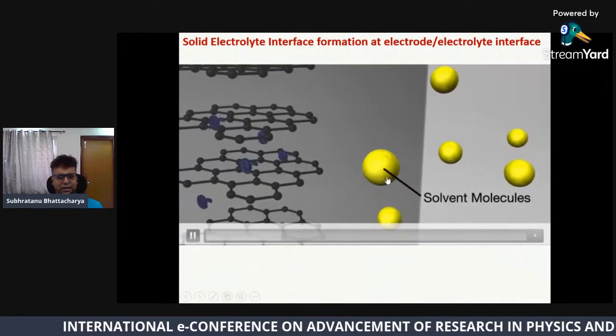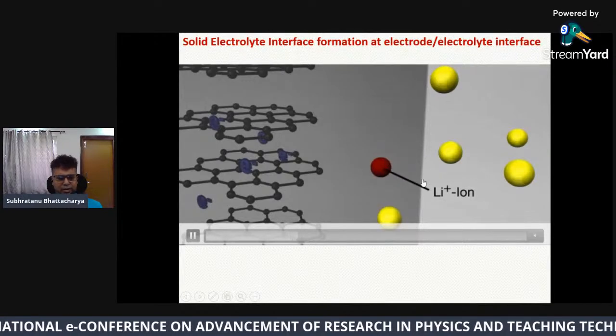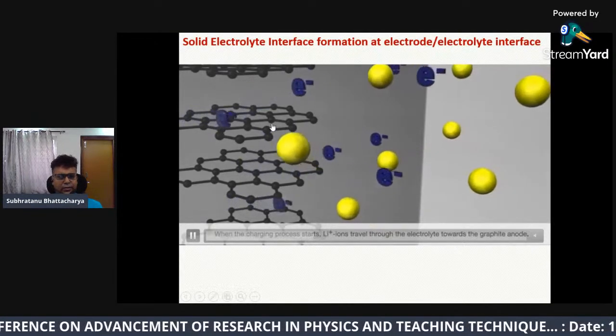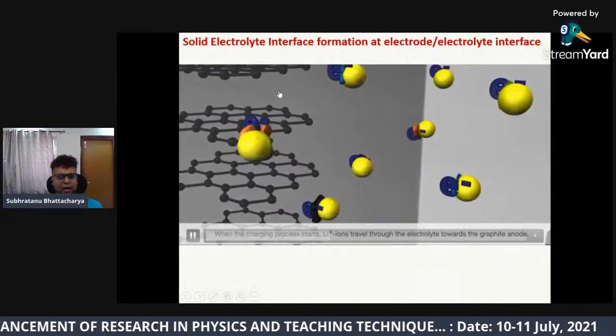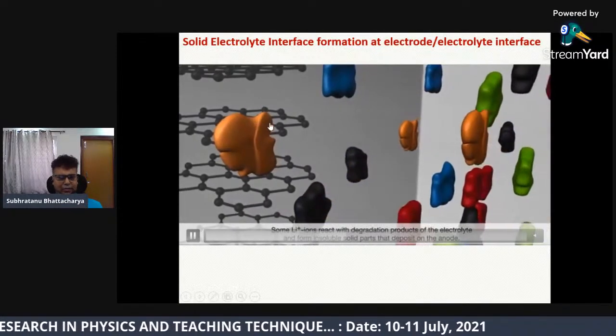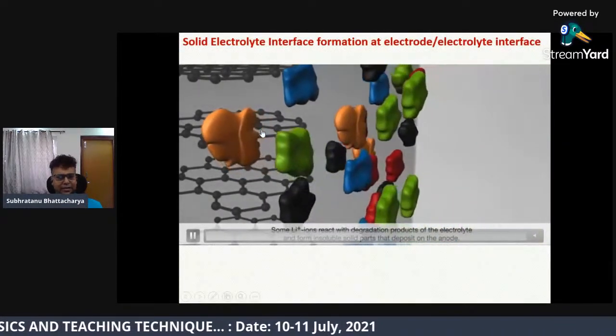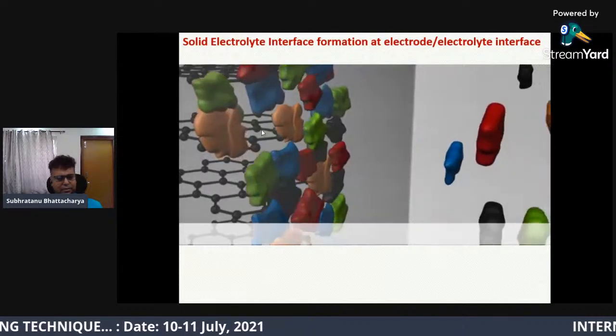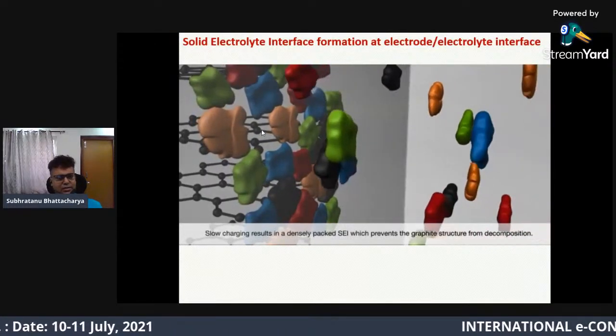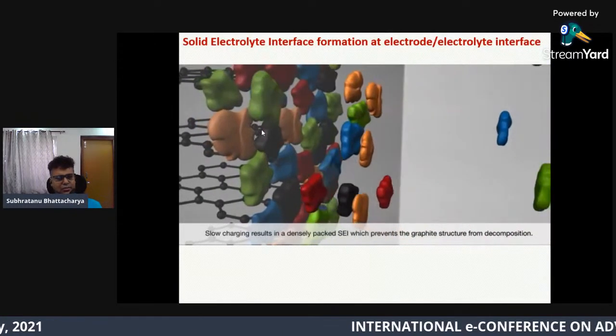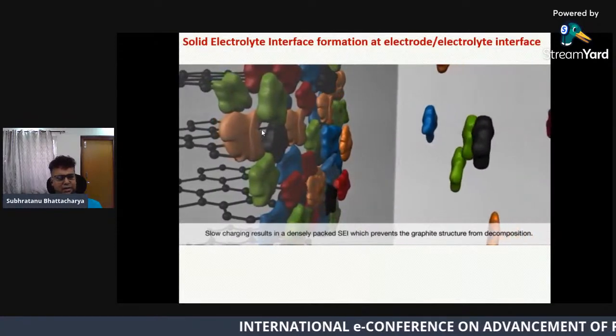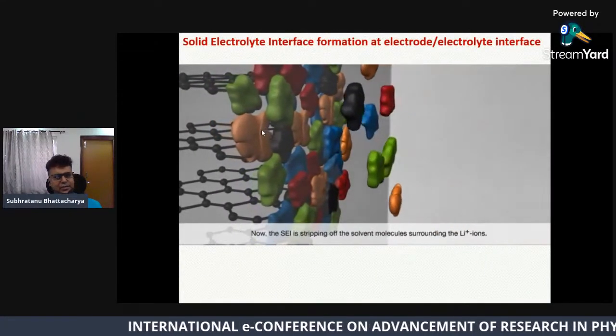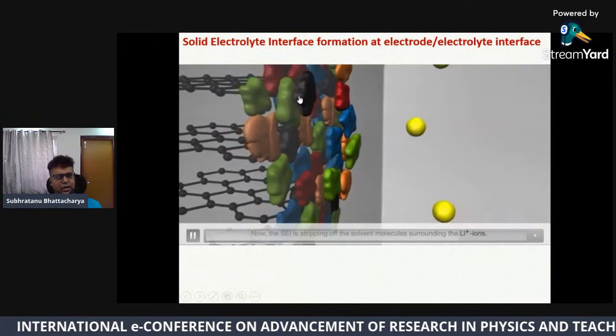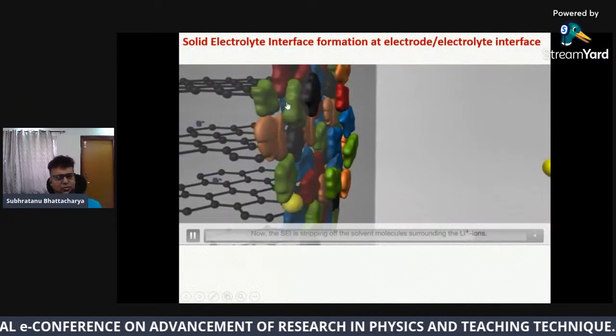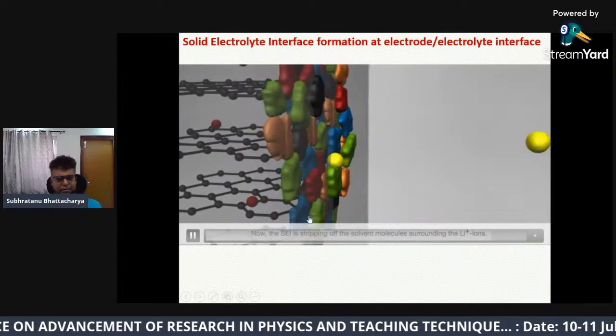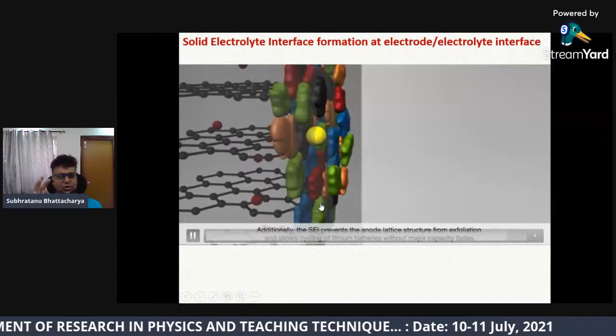So this is how the electrolyte interface works, as you can see. These are the lithium ions, and in front of the anode, which is graphite, there is a layer formation that always happens in the first charge-discharge. In the first two to three charge-discharge cycles, a protective layer forms in the battery. This is called the solid electrolyte interface.